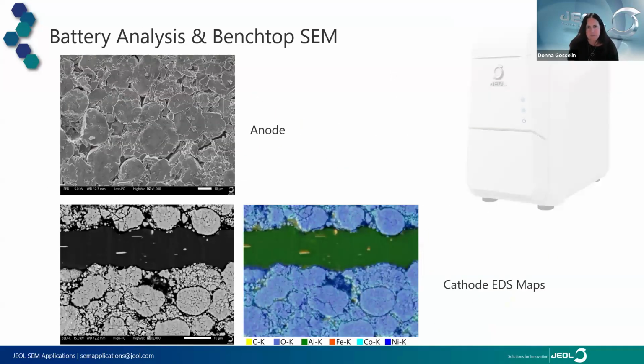So let's start. Here's a quick example of some battery data that was acquired with JEOL's benchtop SEM. It's incredibly easy to use, these benchtop systems. They come at a great price point, and they become quite useful for battery characterization. The top image that you see is an example of anode material analyzed with our benchtop SEM. It was acquired with a secondary electron detector at low voltage, and this highlights really the fine surface structure and coverage of the particles that make up this electrode.